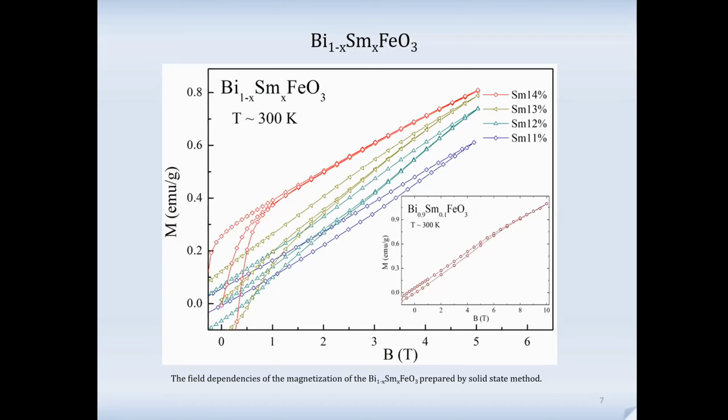The evolution of the isothermal curves shows a smooth change of the magnetization, more or less in accordance with the amount of the orthorhombic phase. The more orthorhombic phase, the higher the magnetization we have. And it's quite convenient to describe the correlation between the crystal and magnetic structure of these compounds.